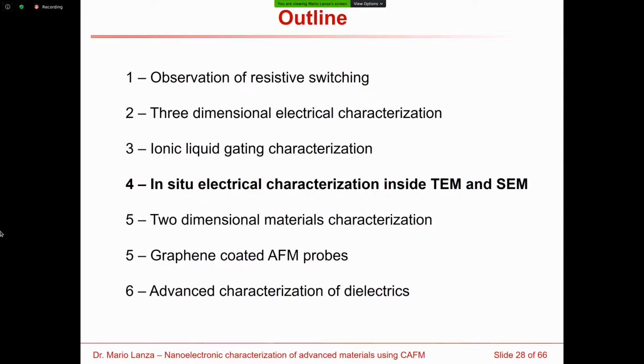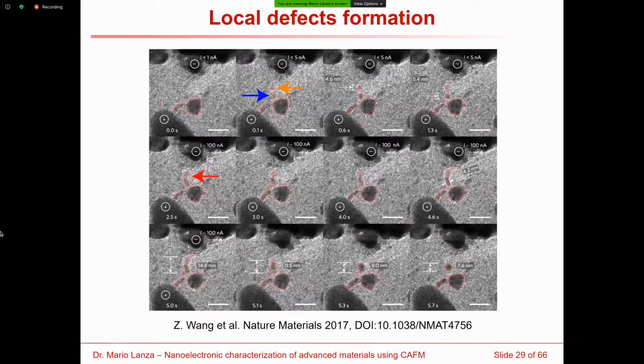So the first one is the formation of local defects in this dielectric using in situ TEM. Here you can see one TEM image in which the authors of this paper take one TEM image for different times as the stress proceeds. And you can see how the filament is forming slowly, and when the bias is removed, this filament is self-disrupted.